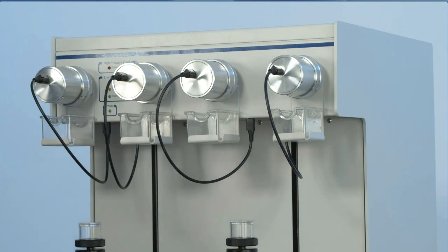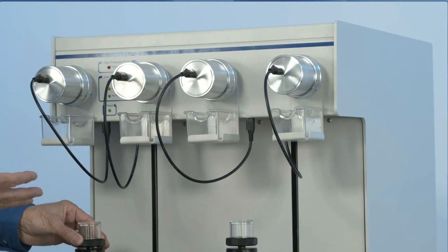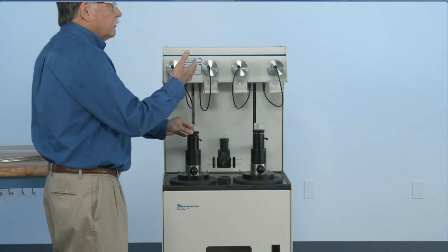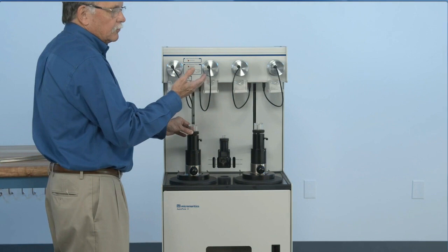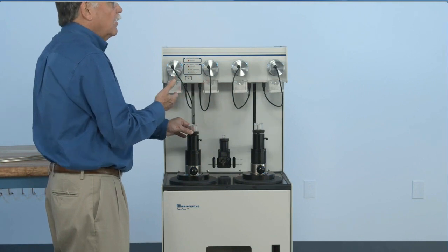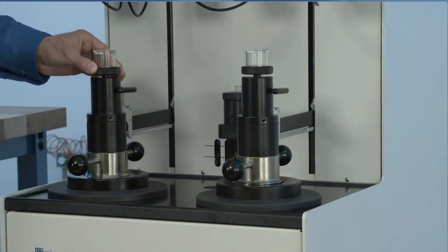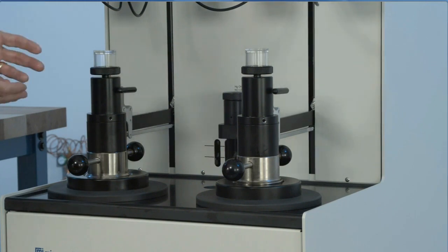But then it is put into the high pressure system, sealed up, and the analysis continues, either up to 33,000 pounds per square inch, which is 227 megapascals, or up to 60,000 pounds per square inch, which is 414 megapascals, depending on which instrument you have.